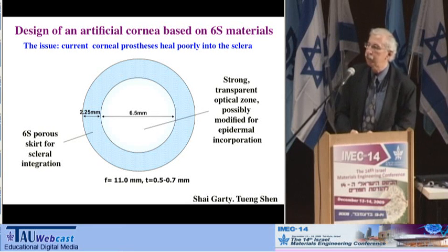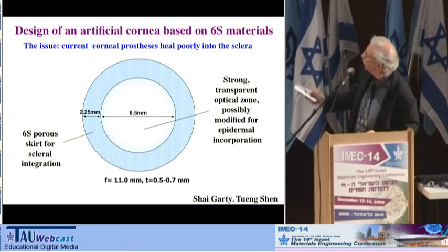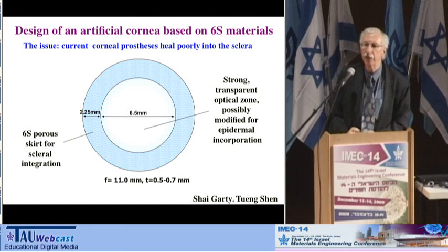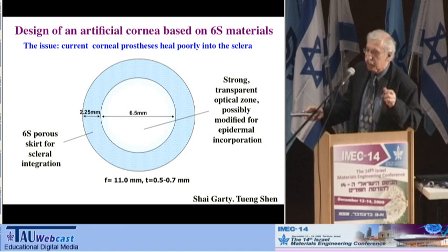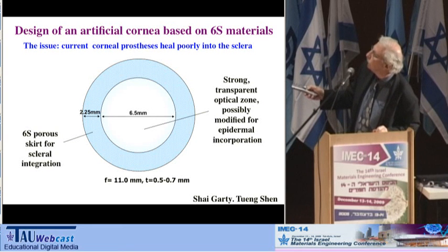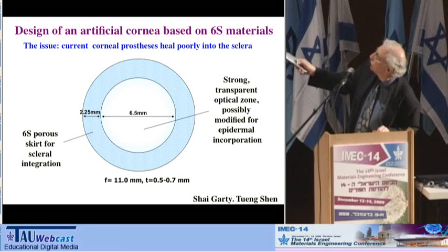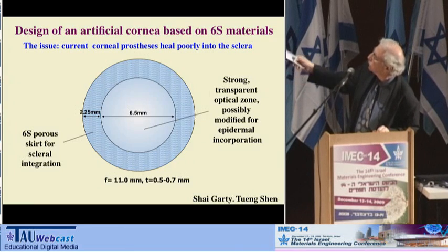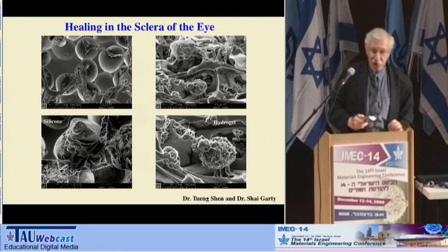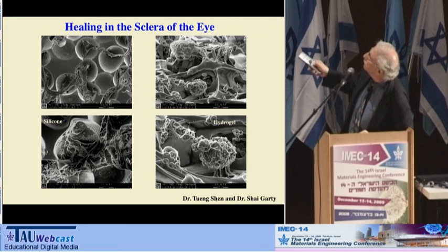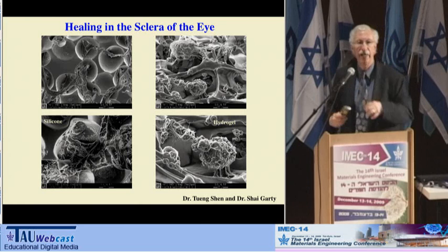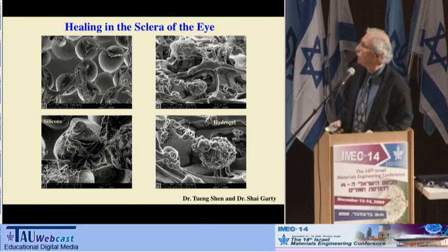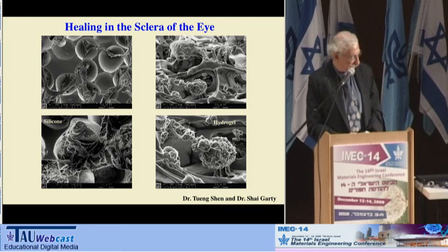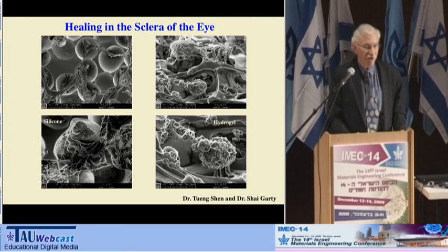And in fact, in a project, Dr. Shai Garti and Dr. Tung Shen in our Department of Ophthalmology and Bioengineering and myself have been making a corneal replacement that also would have a ring, a skirt of this porous polymer, sphere templated polymer, to heal in, and an optical zone in the center. And the initial healing results show a very intense integration of living cells just growing in and out and through this material rather than just scarring it off. And so we're very excited about this development. And again, this is quite a difficult environment to get healing in.